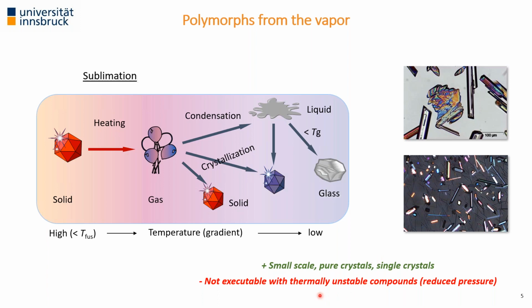The biggest disadvantage, I would say, is thermal stability, because normally sublimation occurs close to the melting point temperature of a compound, and if this is very high, especially with the newer APIs, we often observe decomposition. So then sublimation to thermal stability is a problem, but there may be a way around by reducing the pressure so that we can lower the sublimation temperature and hopefully still be able to produce nice crystals of our compound via the sublimation and vapor deposition procedure.